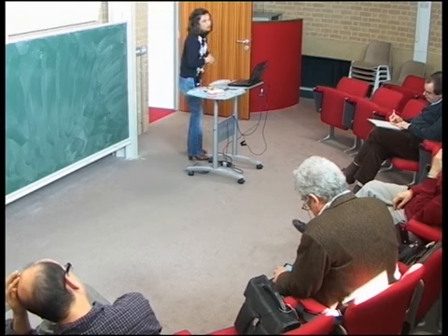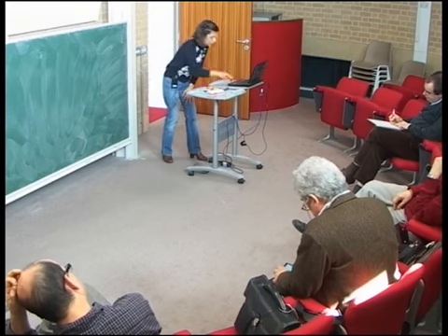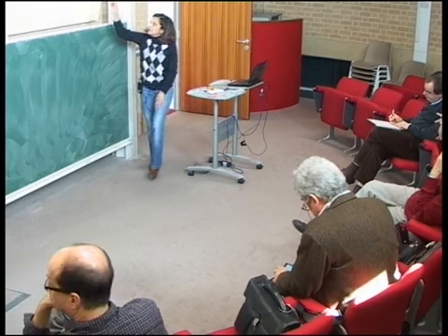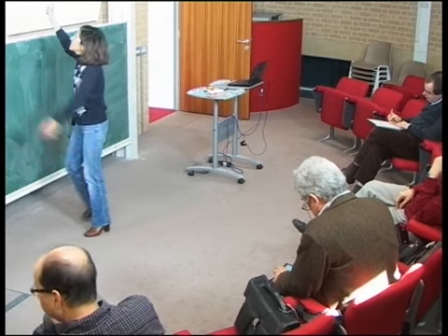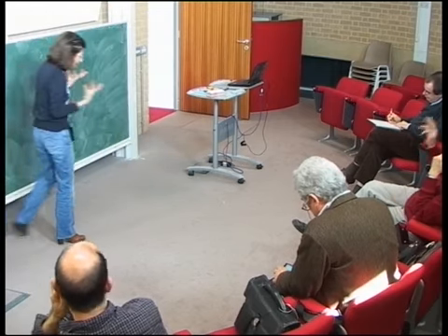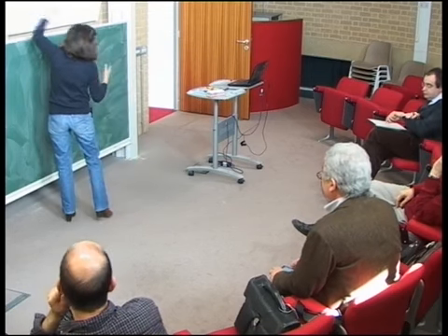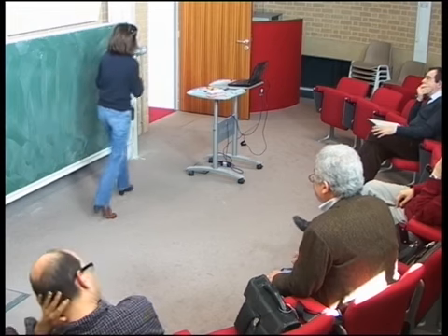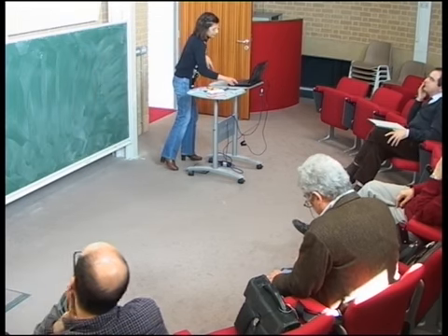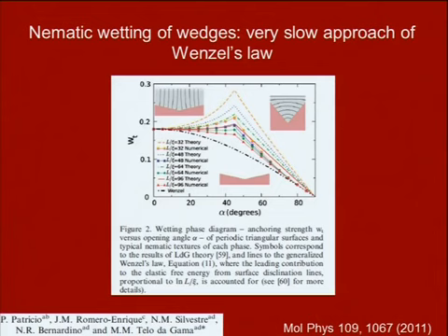Anyway, this is the elastic contribution. The elastic contribution really comes mostly from the defects in this geometry, and the way we can check that is by doing the full numerics, subtracting what comes from the defects analytically, and checking that this difference does not scale with the size of the grooves. And I think this is the full phase diagram. And so here, L over xi goes from 32 to 96.